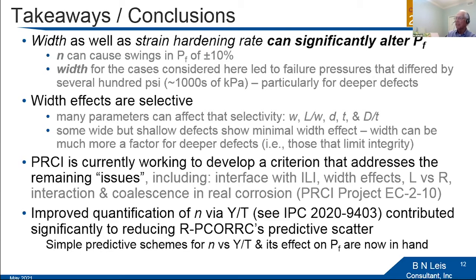Width effects are selective. Many parameters affect that selectivity. And we need a criterion to be developed that will address these aspects in a very robust way. The upside here is that the Pipeline Research Council International is working to develop a criterion to address these remaining issues. They include the interface with inline inspection, width effects, interaction and coalescence, and real corrosion, and so on. And that's a key piece as we move forward, because that's going to bridge a currently significant gap.